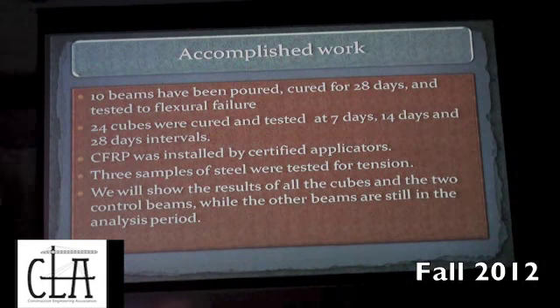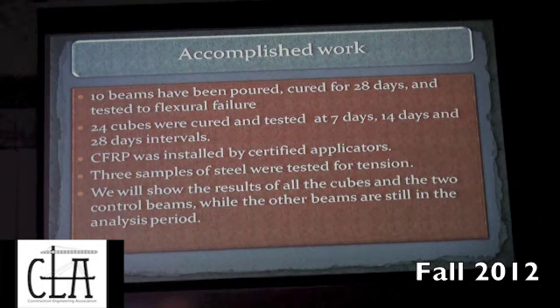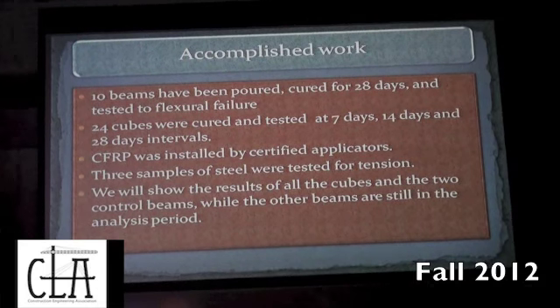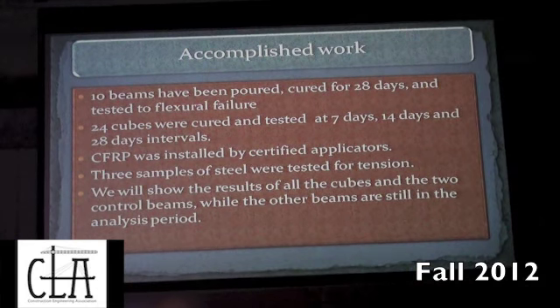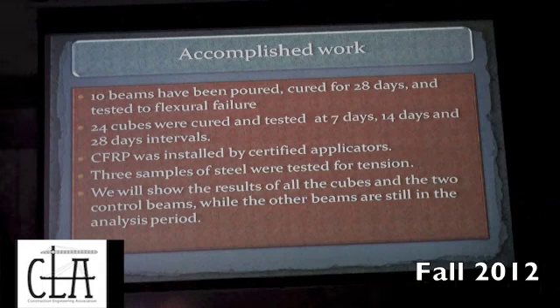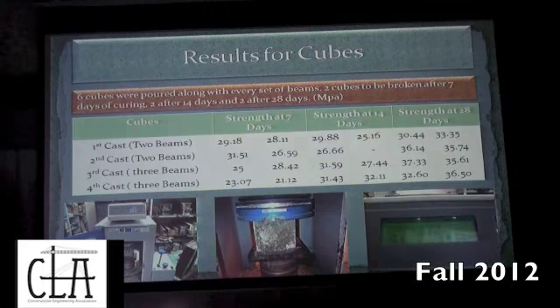Accomplished work: we have 10 beams poured, cured for 28 days and tested in flexure to failure. 24 cubes were cured and tested at 7, 14 and 28 days. CFRP was installed by certified applicators. 3 samples of steel were tested for tension in the mechanical lab. We will show now the results of all the cubes and the 2 control beams, while the other beams are still in the analysis phase.